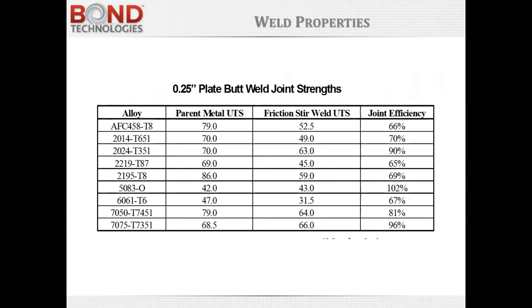This chart shows some typical aluminum alloys and the joint efficiency, which is really the ratio of the stir welded joint to the parent metal. And you'll notice that the 5083 O temper really doesn't lose much ultimate tensile strength after welding because it starts at an O temper, it winds up at an O temper. Others, like the 2000 series materials, have quite a range. And 6061 T6, which is a very common friction stir welding aluminum alloy, has a joint efficiency of around 67% or so.